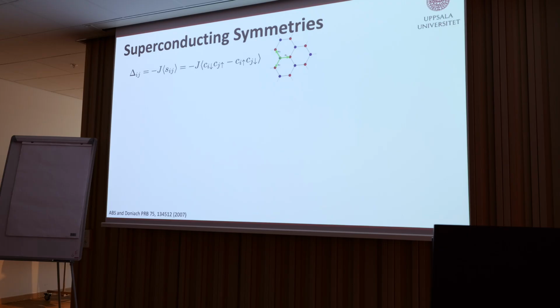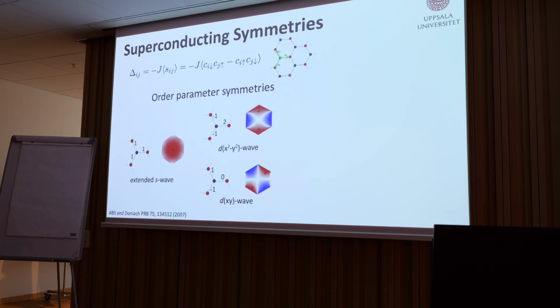Before we continue, it's important to understand what are the possible symmetries I can get from a superconducting state. So I have an order parameter that can sit on all bonds in the material, and I have three different bonds in the honeycomb lattice, 1, 2, and 3. And that means I can have three different symmetry solutions. I first have the s-wave solution, technically an extended s-wave. It has the same order parameter on all three bonds, like this. And if I transform it into k-space, I get a solution that has the same sign in all of the Brillouin zones. So this is an extended s-wave. Then I have two more solutions.